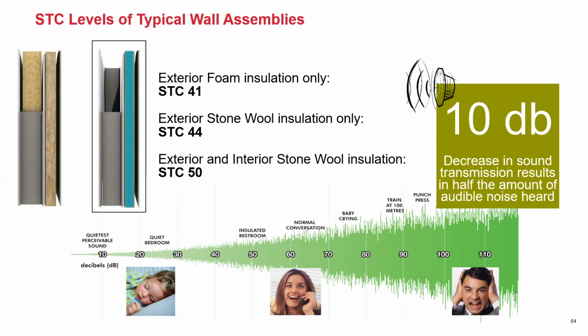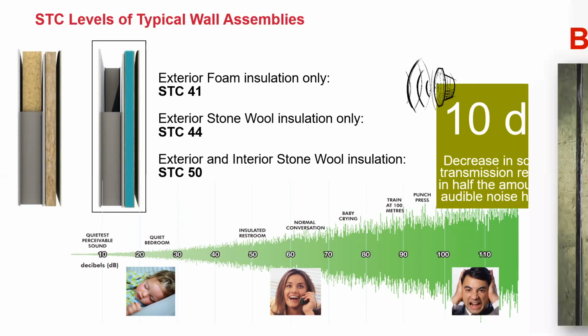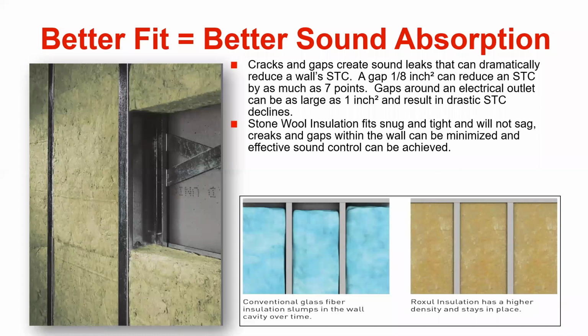And so that difference, let's say between STC 50 and roughly an STC of 41 with foam, is close to a 10 decibel difference. That basically equates to reducing audible noise by 50%. So 10 might not seem like a lot, but it does really reduce the amount of sound that's coming through an assembly. So every STC value does count, and it's something that we are seeing much more considered of late.